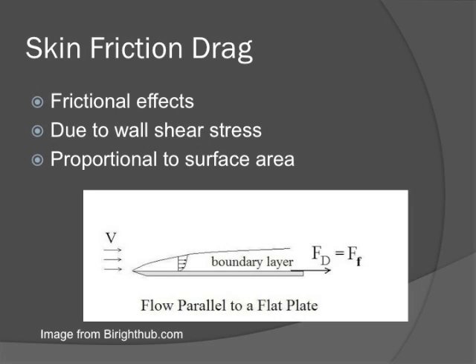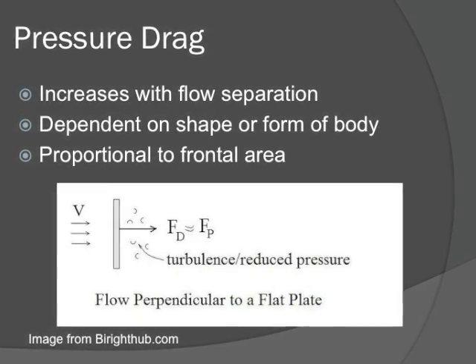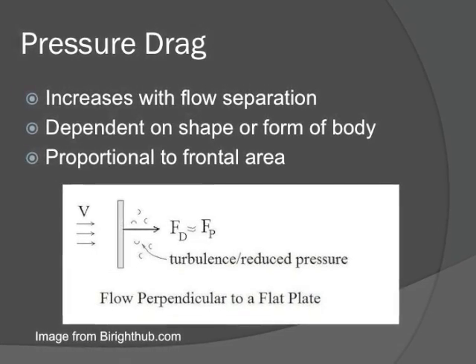Skin friction drag, which is also known as the wall shear, is proportional to the surface area, and the pressure drag is proportional to the frontal area. Therefore, in designing the canoe, we decided to make the front slimmer in order to reduce the frontal area, which reduces the pressure drag, and we made the bottom flatter, which pulls the canoe out of the water, which reduces the overall surface area as it's moving through the water.